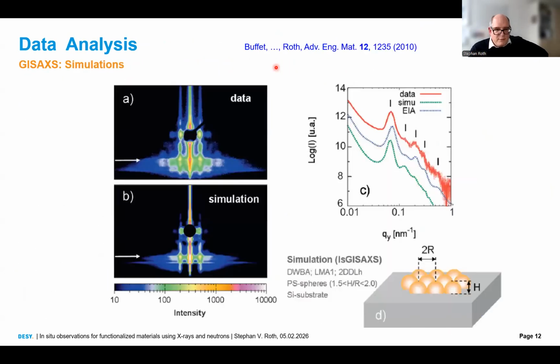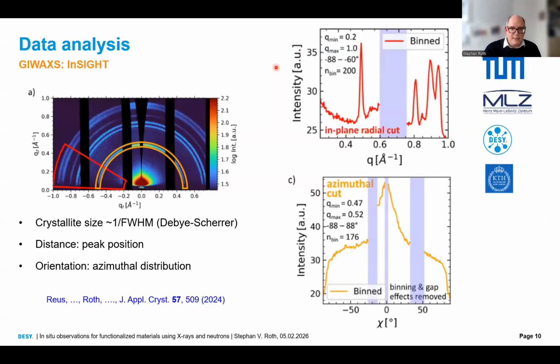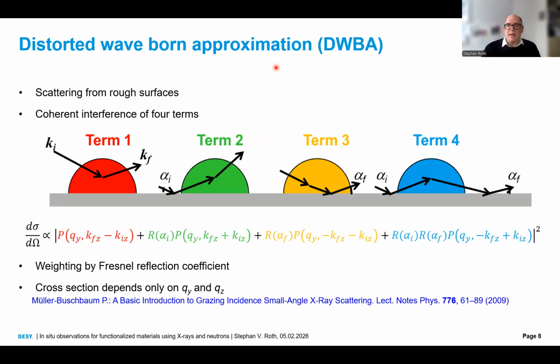No problem. So what we do is we assume a certain real space model. So we put real structures on the surface. You say this is a hemisphere, this is a full sphere. It can be more than one layer. I have a substrate or maybe an intermediate layer. And then I simulate these scattering processes. Here, it's not really ray tracing, but I know from Born scattering, this is beam in, beam out, and I scatter here at the scattering center. This gives me the form factor scattering or the Born approximation, what you know from transmission scattering.